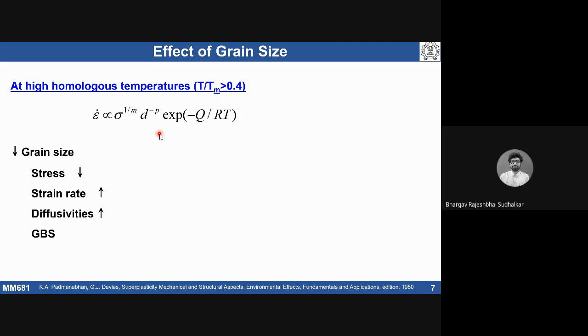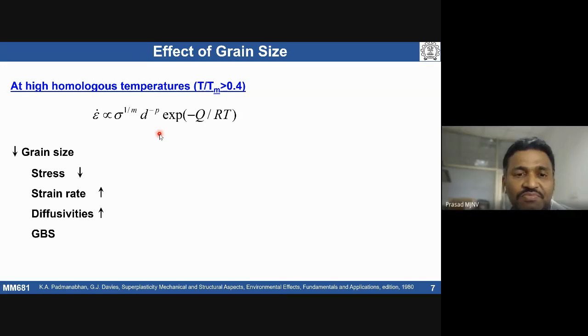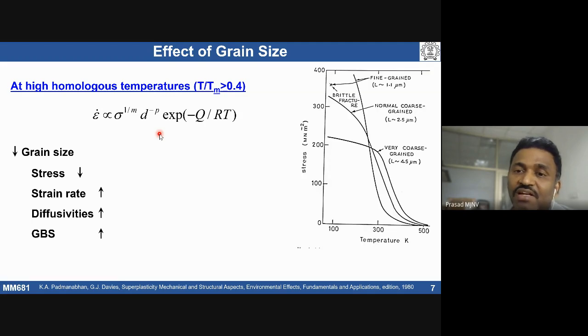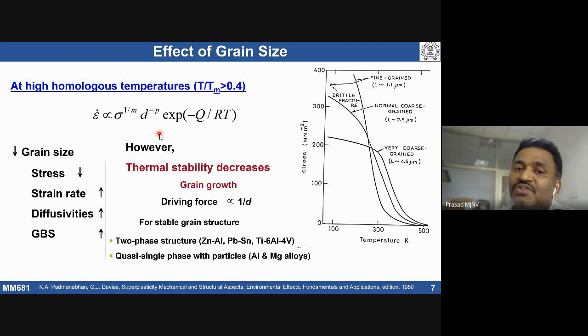Grain growth occurs. Fine grains can undergo easy grain growth. Grain growth, the thermal stability, is one of the major issues. If you go for finer and finer grain size, thermal stability is one of the major concerns. The driving force for grain growth is inversely proportional to curvature; the curvature basically we talk about in terms of grain size. So in pure metals, even if you have a fine grain size, the moment you take it to elevated temperatures, it is going to undergo grain growth. Then all your beneficial effects are going to be lost.